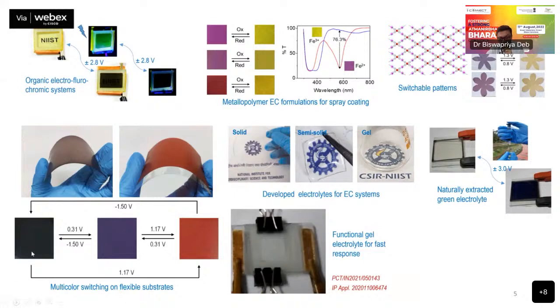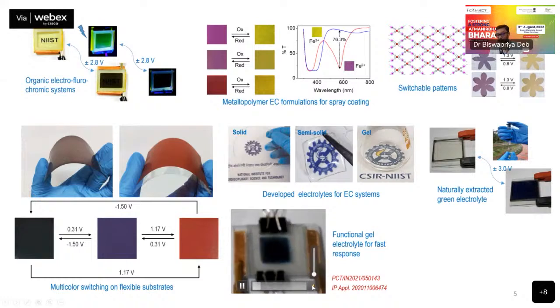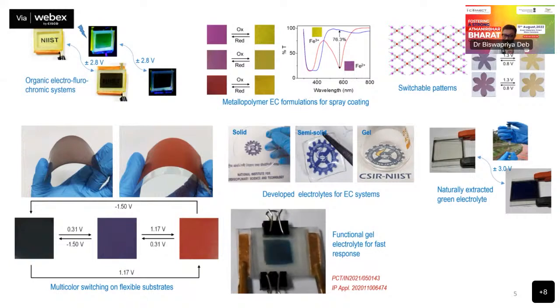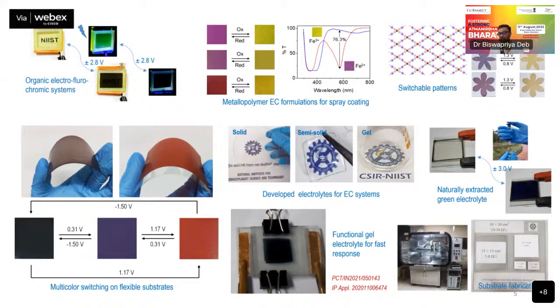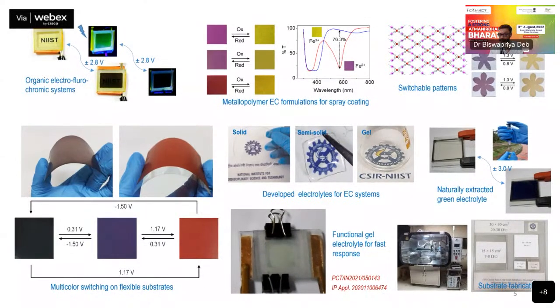We have special electrolytes, like this functional gel electrolyte that can give you very fast switching, probably not required for a window, but for a car mirror. These kinds of systems are available, and we also have a process for making conducting substrates using a spray pyrolysis system inside CSIR-NIIST. And in other labs, as Dr. Lele already mentioned, we have silver-based systems or aluminum-doped zinc oxide based systems in many other CSIR labs. So basically, in CSIR you can get the whole nine yards for any kind of this smart glazing technology.